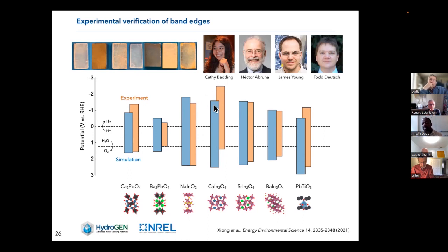And further analysis, again, enables us to refine our model. And it turns out that in that case, it's mostly due to the presence of oxygen vacancies at the surface. So when you have a material that has oxygen vacancies, it tends to be more electropositive. And because of that, the band gap gets shifted up. And as a result of this, we get this disparity between experiment and theory. So this is also something that is very important for us. The feedback being that we also need to take into account the surface termination in order to properly determine the energy levels of the semiconductor when it comes to splitting water into hydrogen.